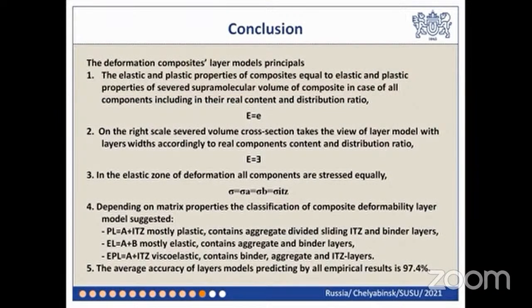The application of layer models and composite elasticity prediction were suggested and proved. The modeling is based on classic composite structure elements such as matrix and aggregate. The matrix, except binder, includes contact zone ITZ, where adsorptive bonds dominate. Composite deformability research confirms that ITZ is the main factor of plastic deformations of composites. Thus, the deformation modeling principles were formulated in this presentation.